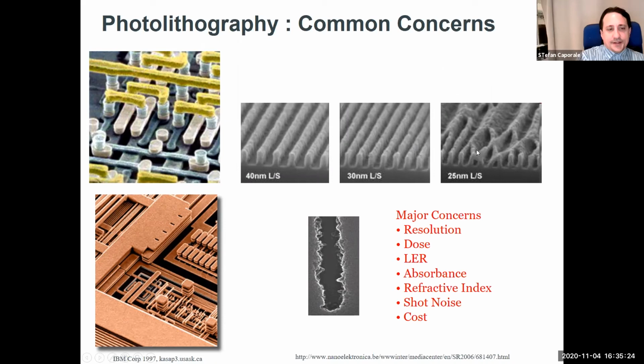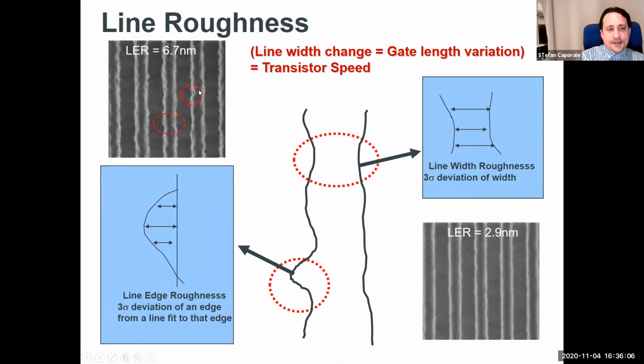So as we're getting smaller and smaller, and as we're developing new materials, you can see this is the same resist printed at 40, 30, and 25 nanometers. And you can see as it gets smaller, this resist starts to get rounding, and then the lines start falling over. So this gives us an idea of the ideal resolution of that material, and different materials, depending on the height and the width that's here, are designed for different applications. So the amount of dose that it can take, and then a big problem is the roughness. So this is an example of some very bad roughness coming on here. And this is an example of probably the biggest issue and concern, especially as we're getting smaller and smaller, is we don't make a perfect line and space like I drew in PowerPoint.